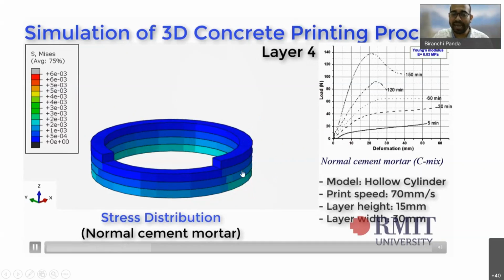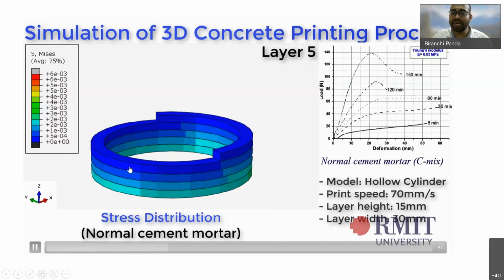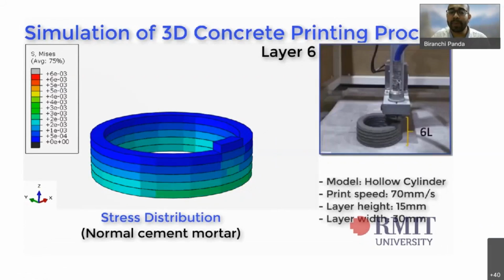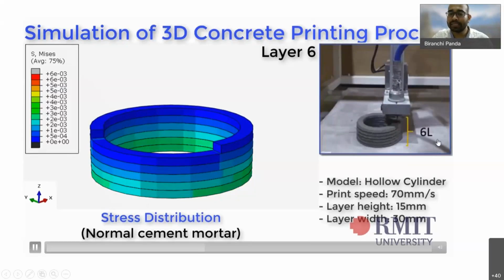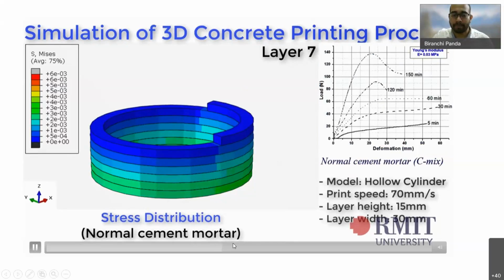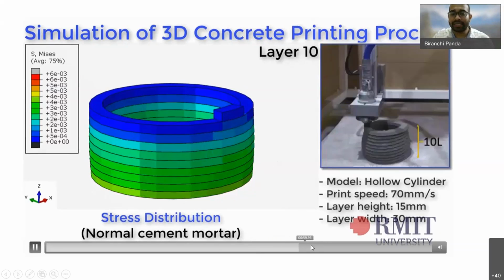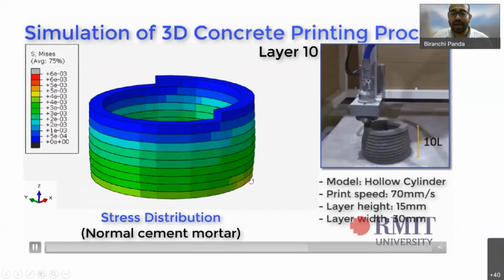So depending upon the height of the structure you are printing, this stress has been simulated in this model, so that we can predict the number of layers we can print. And it has been compared with the experiment. You can see 6 layers depositing here, and here also 6 layers. So when you are going towards the end, it is going to collapse because of higher stress.